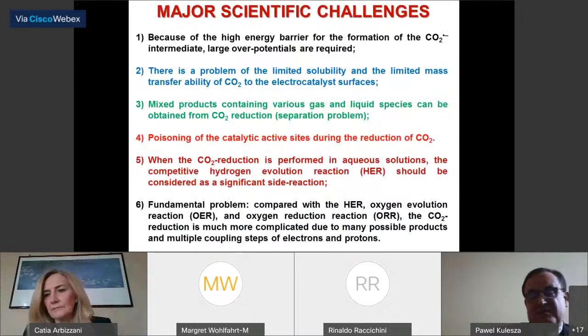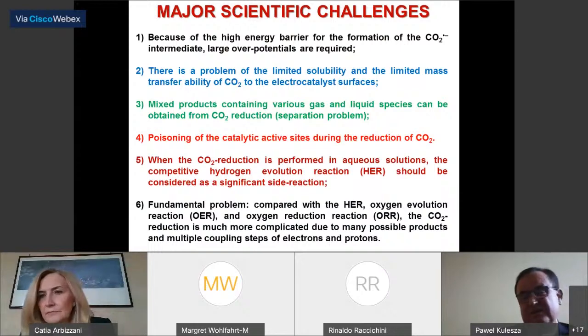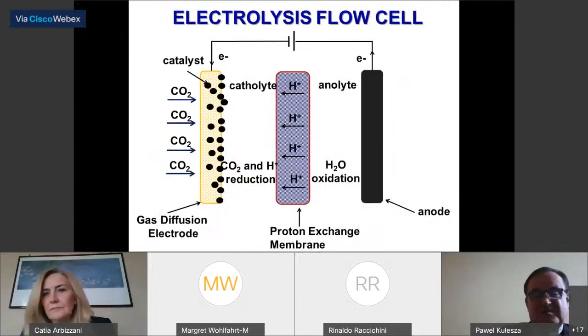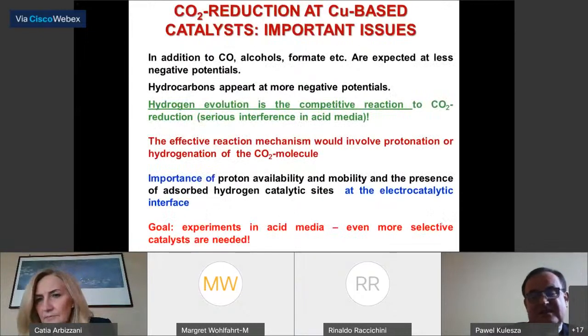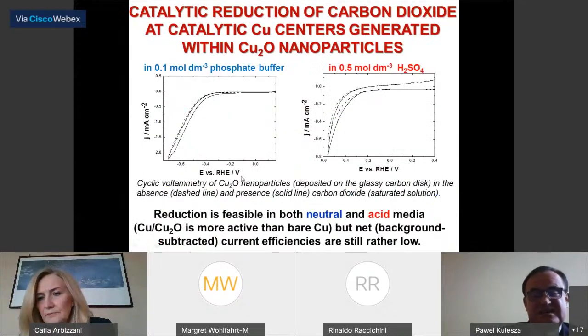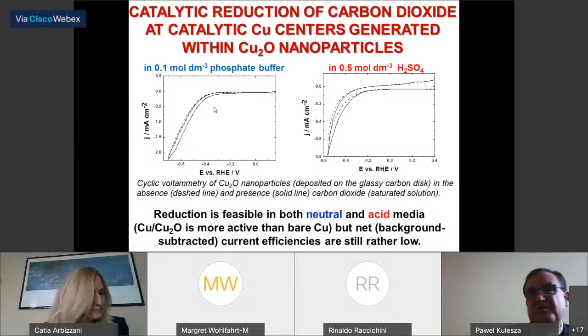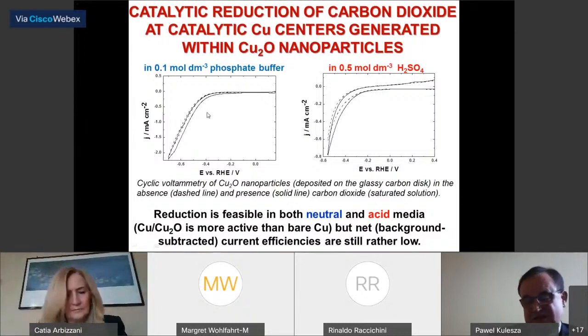But there are many problems of carbon dioxide reduction, in addition to high overpotentials, necessity of activation of the molecule, competitive hydrogen evolution, very inert system. We are interested in building electrolyzers too. And it's very interesting that we can, this is a typical example. The reduction is basically dominated by hydrogen evolution. It would be nice to do it in acid medium because the systems use membranes.